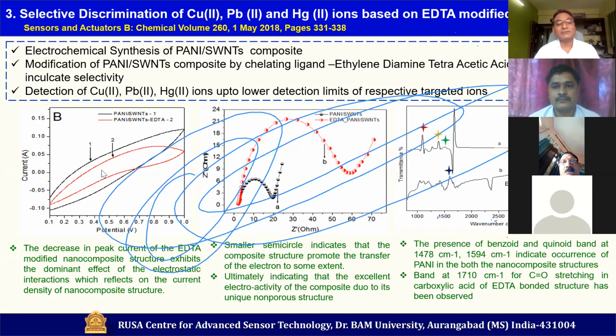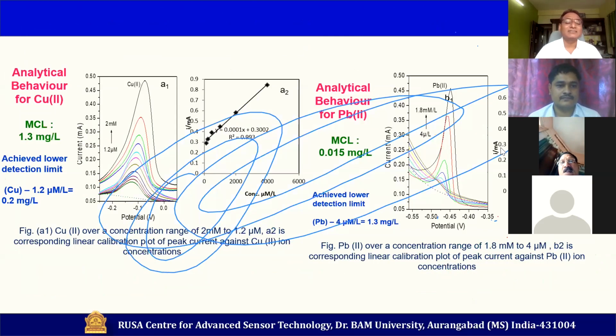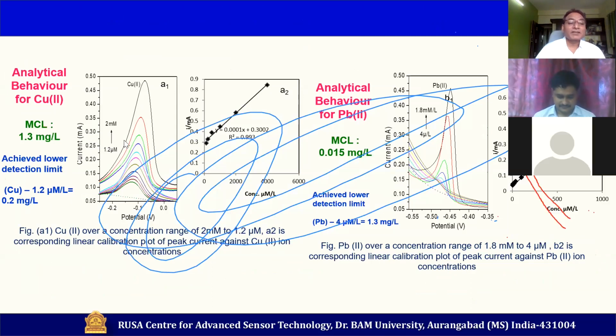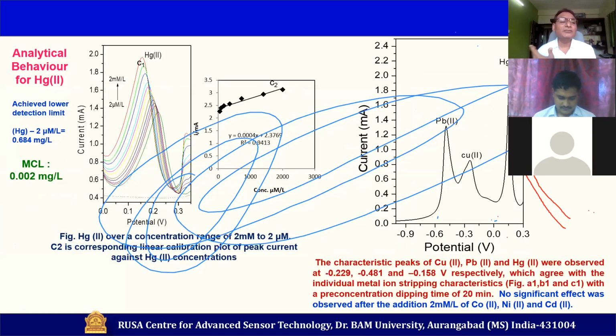And again we did the same investigation, CV, and then you can see this is EIS study, and then this is FTIR spectra. We can see this clear-cut distinction. And then I will be focusing more on sensing results. You can see here copper, we could enhance further. You can see earlier it was a little bit lesser than this, but with this approach, our low detection limit was 0.2 mg, right? And as far as the lead is concerned, we could not get any significant enhancement. The composite of PPY with SWNT was better. This was not at all better, right? So this is how we need to understand, right?